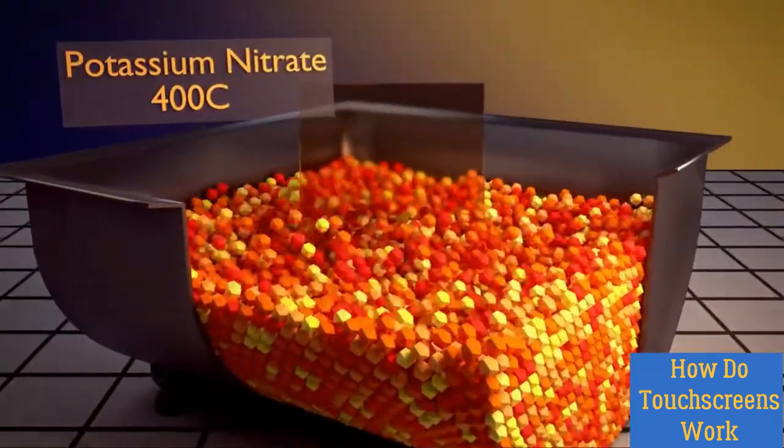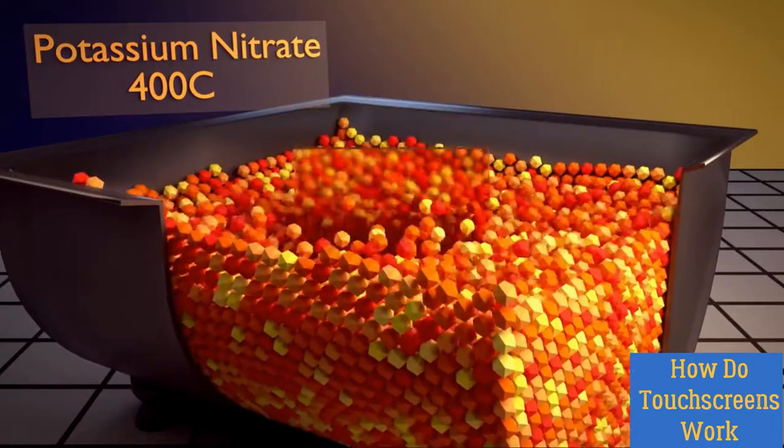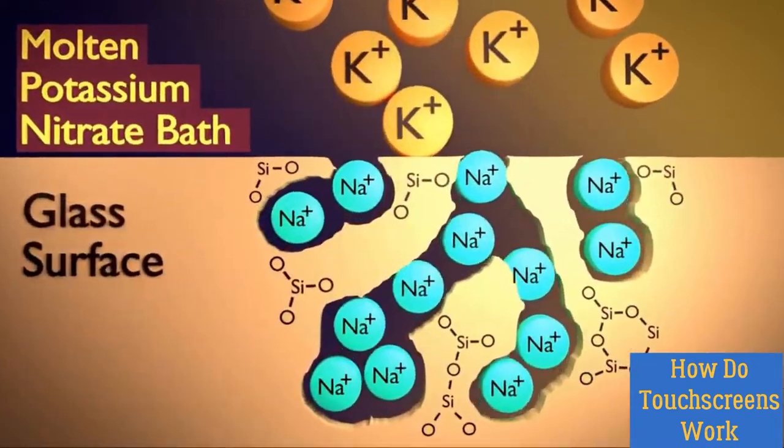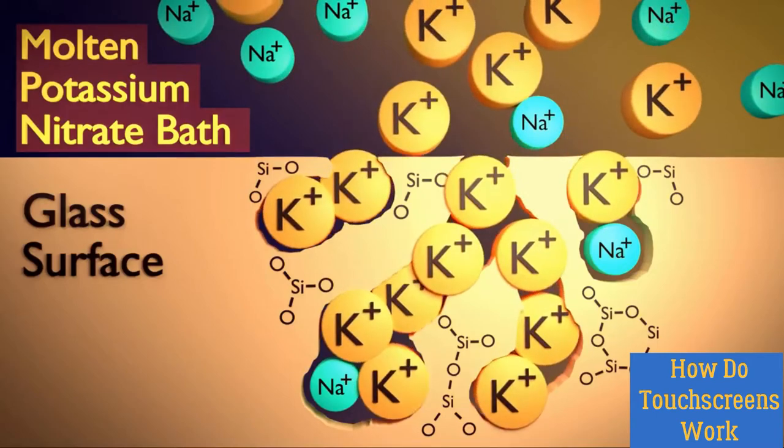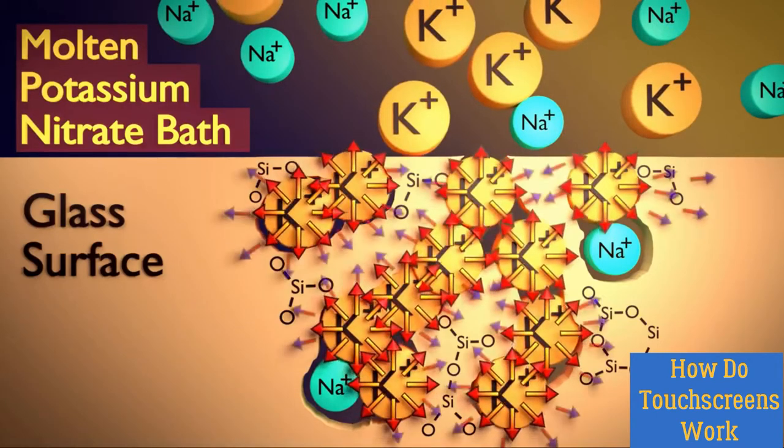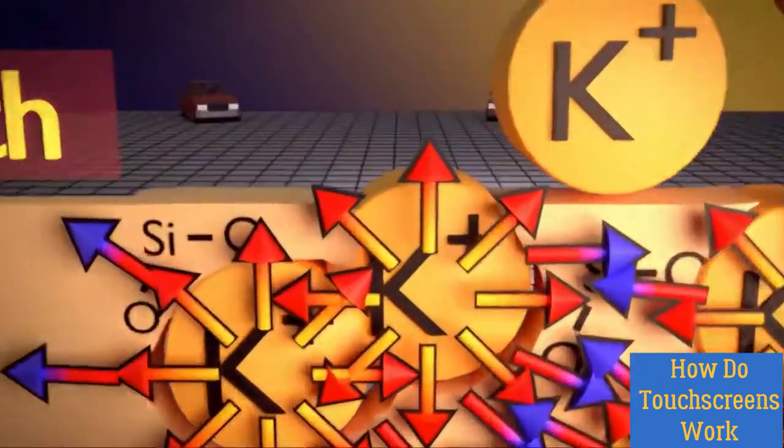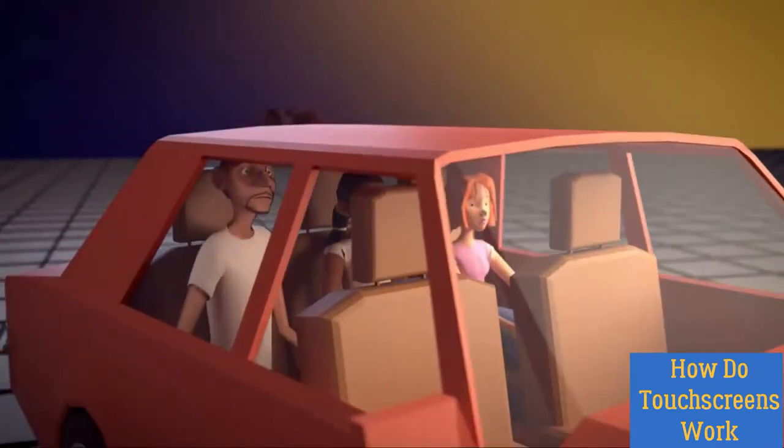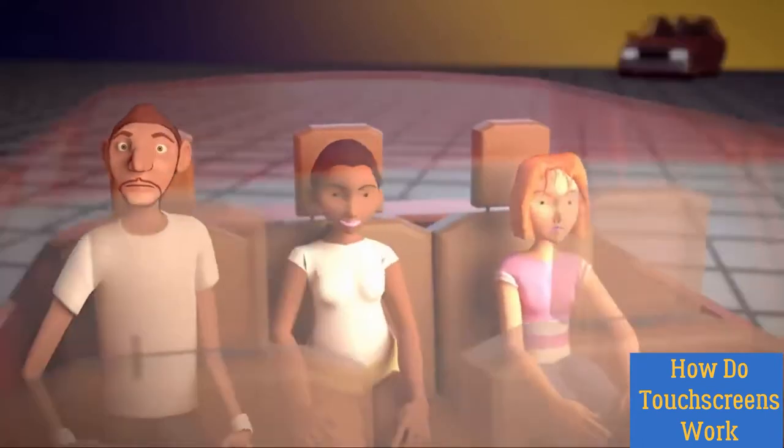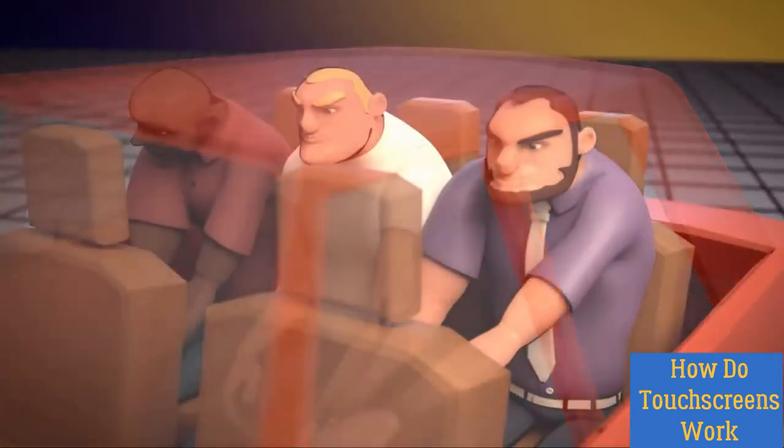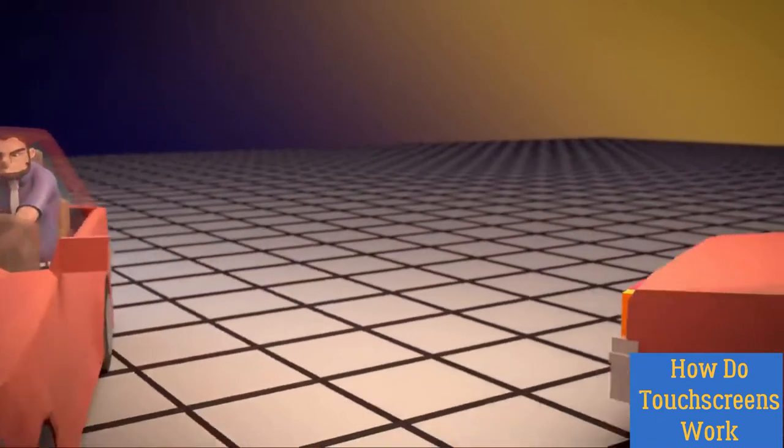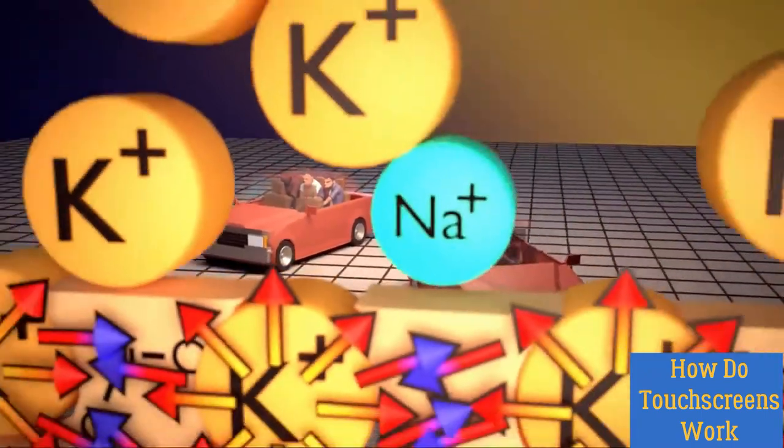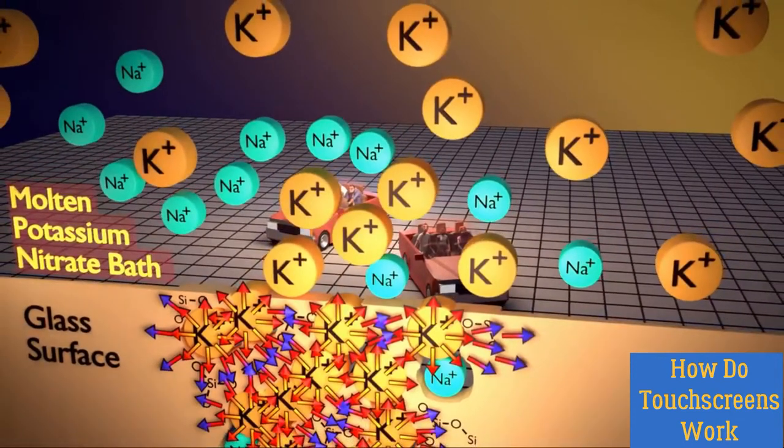A smartphone's glass is an aluminosilicate glass that is toughened by soaking it in a bath of potassium nitrate. This causes the sodium atoms in the glass to migrate out, and much larger potassium atoms to take their place. Because the potassium atoms are much larger, they generate a substantial compressive force on the surface of the glass. Here's a quick analogy. Imagine filling the backseat of a car with three average sized people. They fit snugly, but if you push them, they're still able to move. Now replace those three people with three football linebackers. Those linebackers are just flat out stuck, unable to move. It would take much more force to move those linebackers from their seats. This is the fundamental concept behind what makes toughened glass special. The atoms are compressed so it would take much more force for the glass to break.